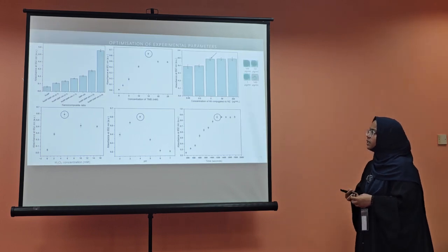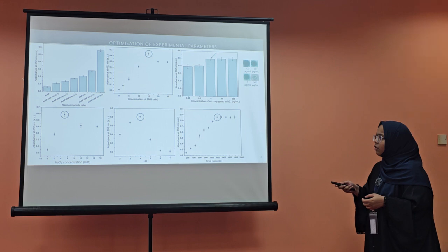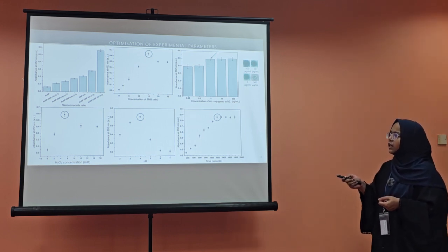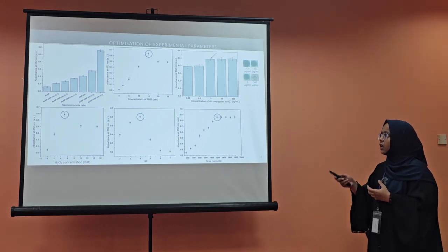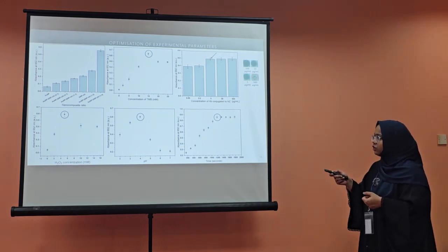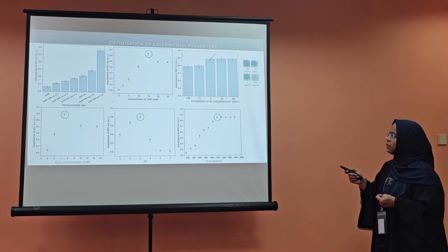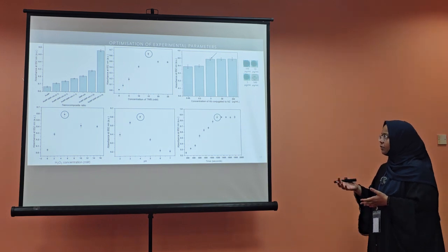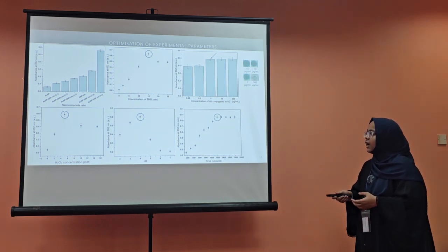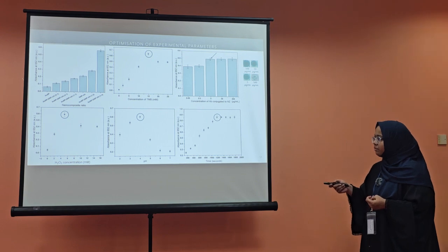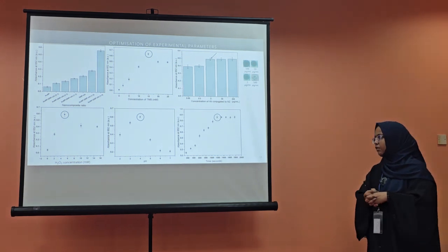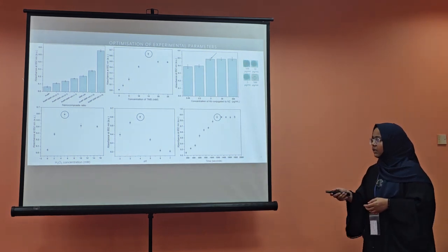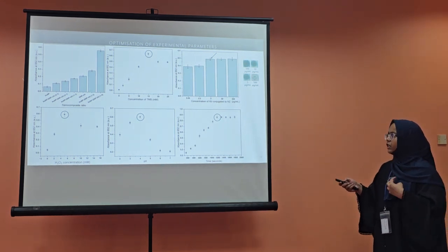Several experimental parameters were optimized, including the nanocomposite ratio. The best activity was observed when gold nanoparticles and graphene platelets were combined in the ratio of 1:1. That was the optimized ratio of the nanocomposite. The concentration of TMB was optimized to 15 millimolar. The concentration of antibody conjugated to the nanozyme was optimized to 5 microgram per ml. Hydrogen peroxide concentration was optimized to 5 millimolar. The pH of the sodium acetate buffer was optimized to 4. And the time of the immunoassay was optimized to 10 minutes upon the introduction of TMB into the solution.